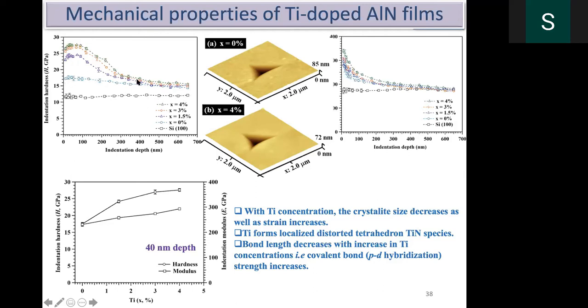Of course, definitely the hardness increased, but after a level, it decreases and stabilizes around 16, 17 GPa. This is basically called the indentation size effect. That's why the hardness goes up suddenly, comes down and stabilizes. Suppose you plot the titanium percentage versus the hardness at one particular depth, for example, either 200 or 100 nanometer depth, the hardness increases with the addition of titanium. Anybody can see that very clearly. That's what I have mentioned here.